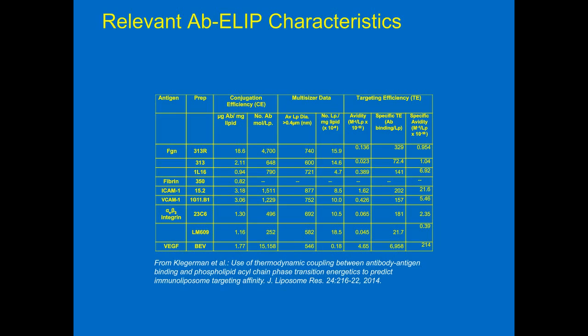Great. Our next question, one viewer asks, what is your preferred technique for counting nanoparticles? Well, the Multisizer is the best out there. Now, I didn't talk about what people typically use to enumerate their nanoparticles. A lot of times they use electron microscopy, which is rather laborious, especially when you have to count 300 or more particles to get a meaningful or a useful distribution and a number.